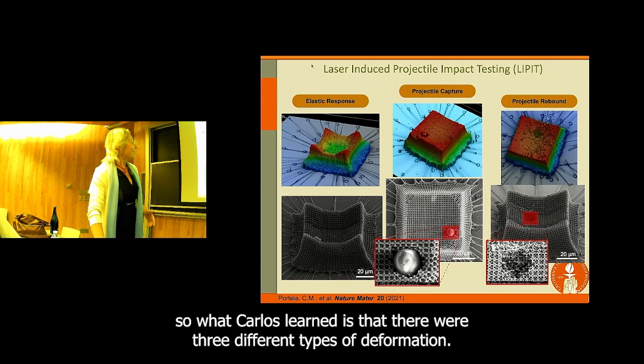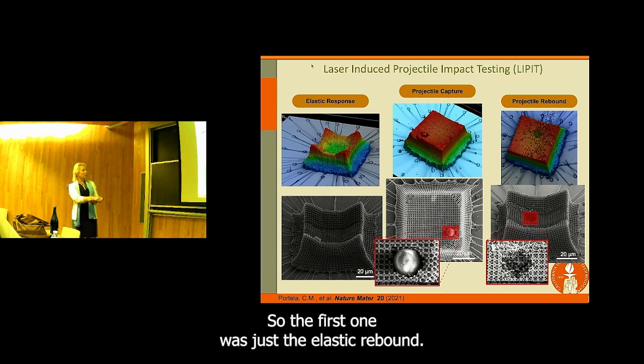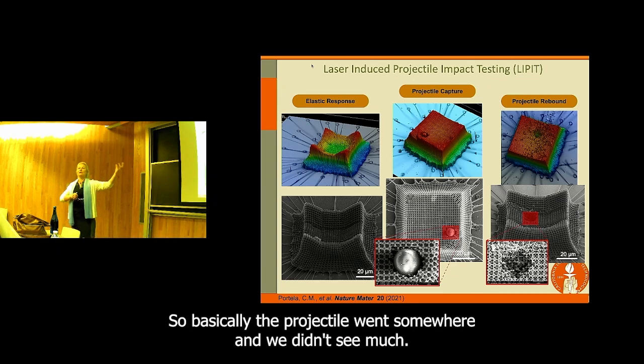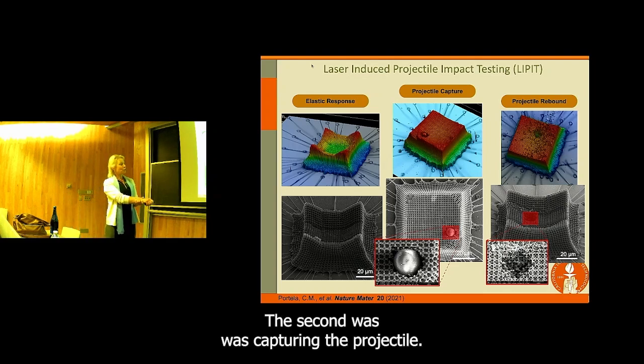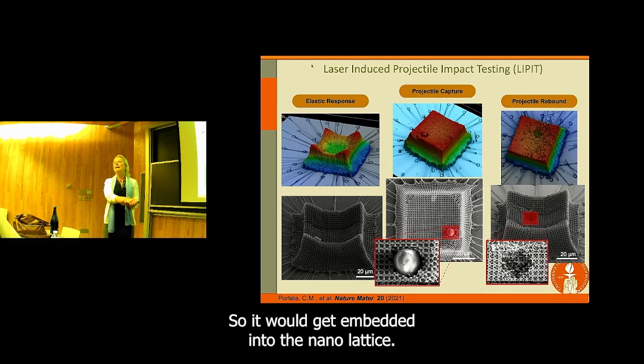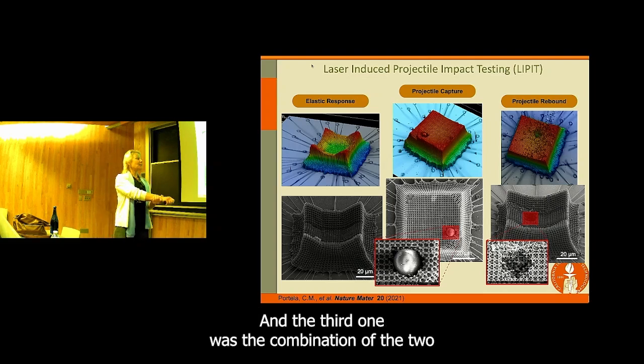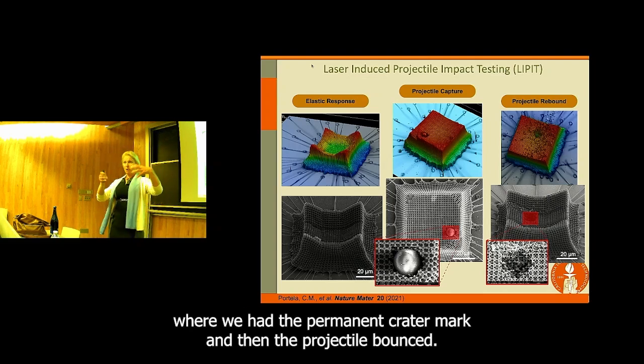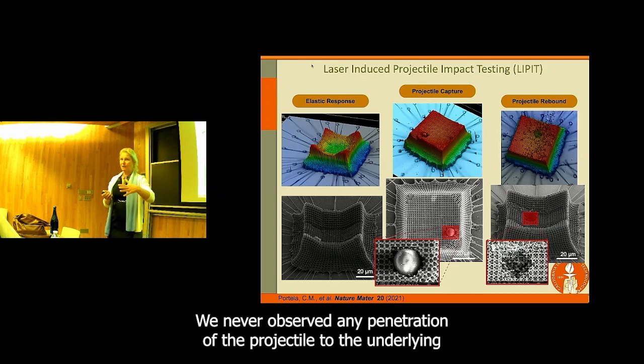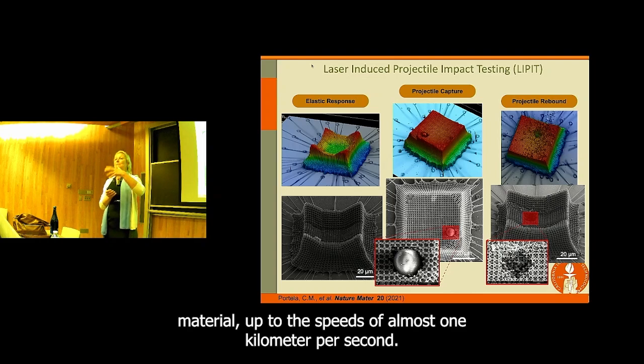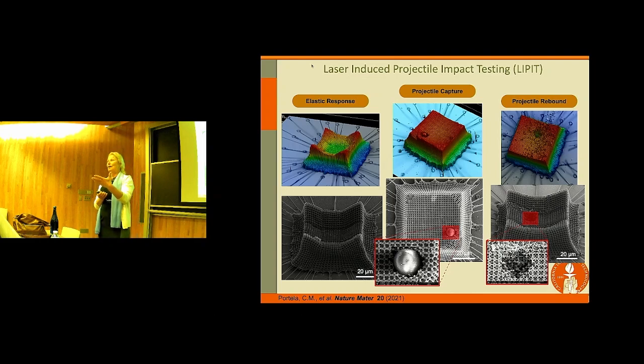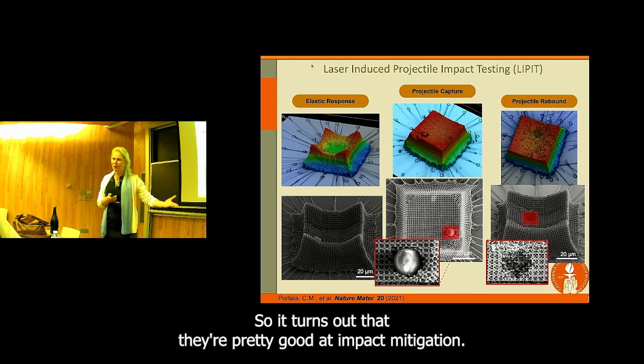All right. So what Carlos learned is that there were 3 different types of deformation. The first one was just the elastic rebound. So basically the projectile went somewhere and we didn't see much. The second was capturing the projectile, so it would get embedded into the nanolattice. And the third one was the combination of the two, where we had the permanent crater mark, and then the projectile bounced. We never observed any penetration of the projectile into the underlying material up to speeds of almost 1 kilometer per second. So it turns out that they're pretty good at impact mitigation.